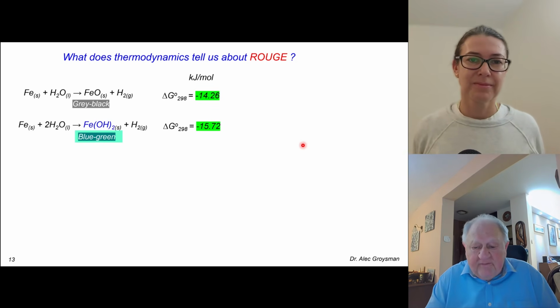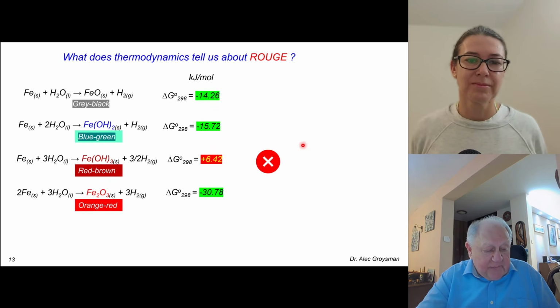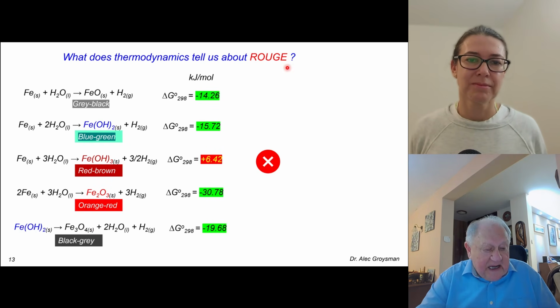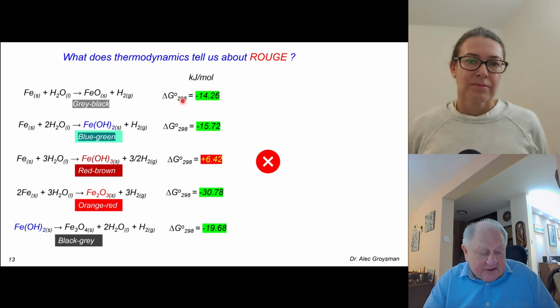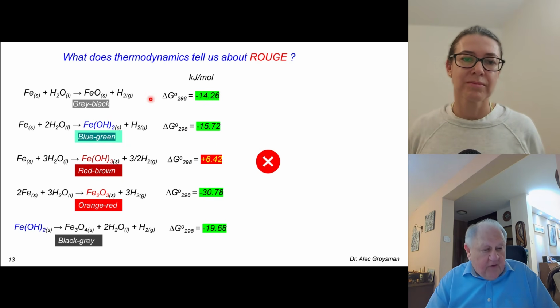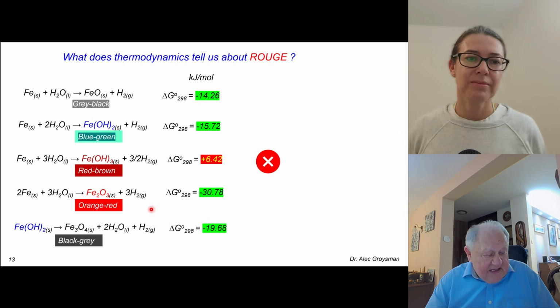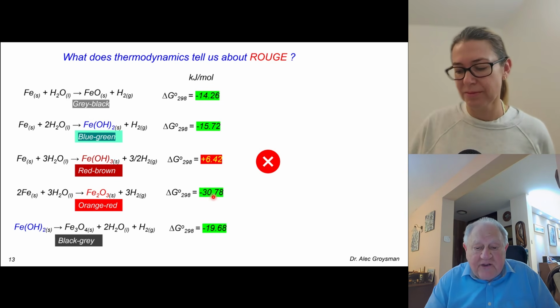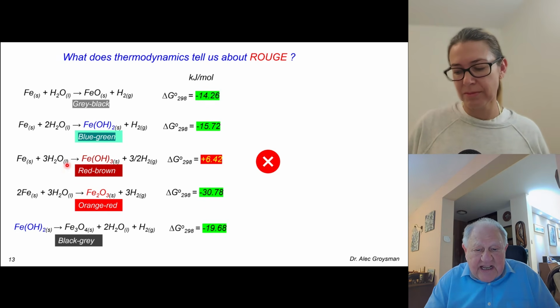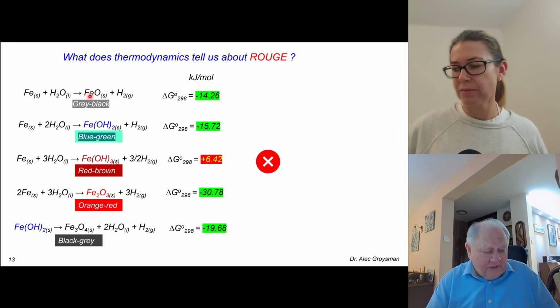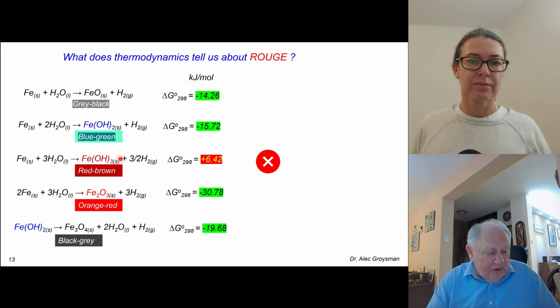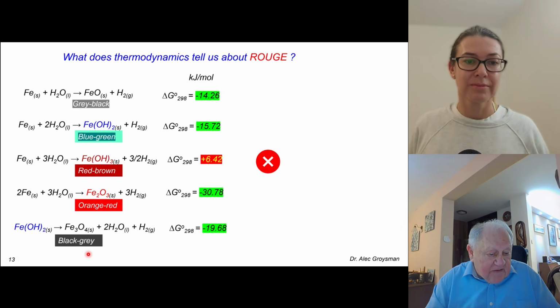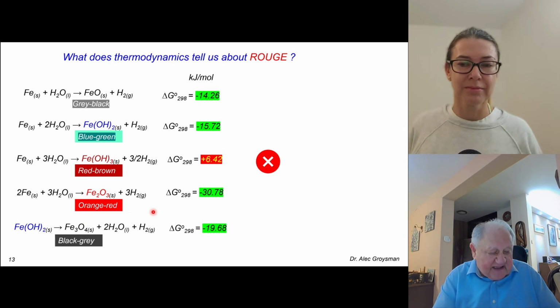And I show you 5 possible corrosion reactions between iron and water. Calculations of Gibbs energy for these reactions show that for four reactions, this energy is spontaneous because delta G is negative. But for this reaction, as you see, it is positive. Therefore, this reaction cannot occur. As you can see, different oxides and hydroxides are formed with different colors: gray black, blue green, orange red, and black gray, exactly as a parade of colors of rouge.